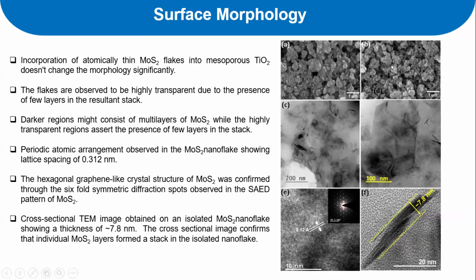This means the 2D layered MoS2 is atomically thin. They don't really block the porosity of the material, which means they can cover the surface conformally on top of the titanium dioxide nanoparticle network. So it is a very good surface addition, and they are coated properly on the material, as we can see. A lot of pores are existing. And if you look at the 2D layered material surface morphology, they are extremely thin. These are figures C and D.